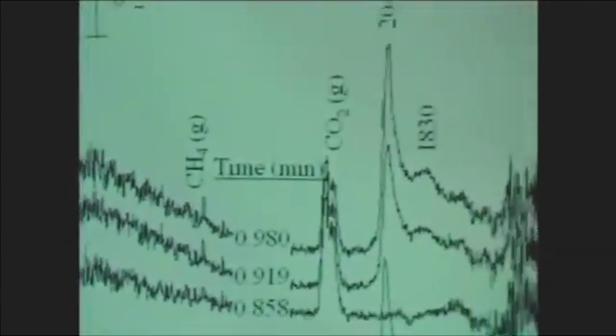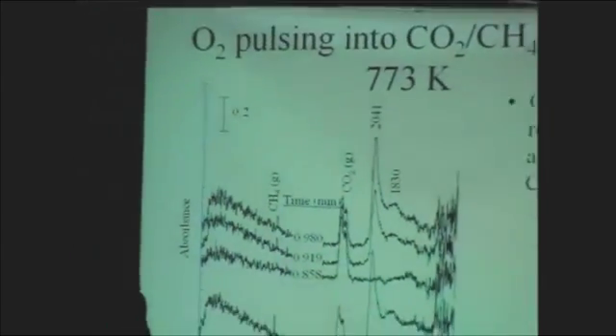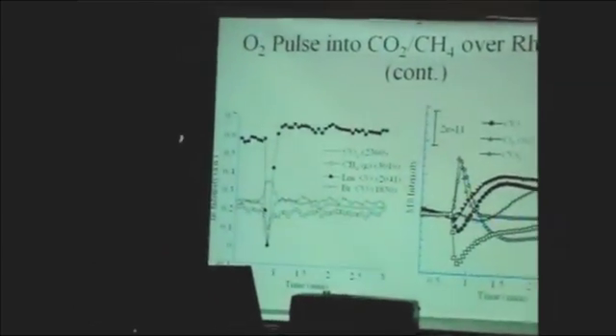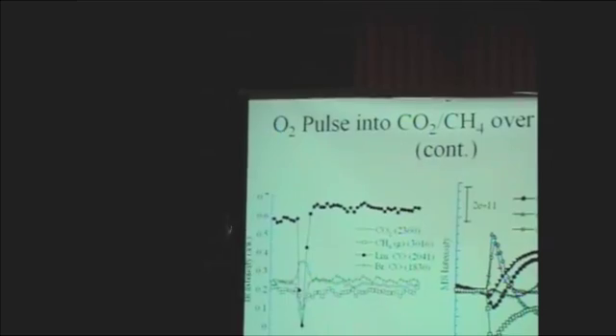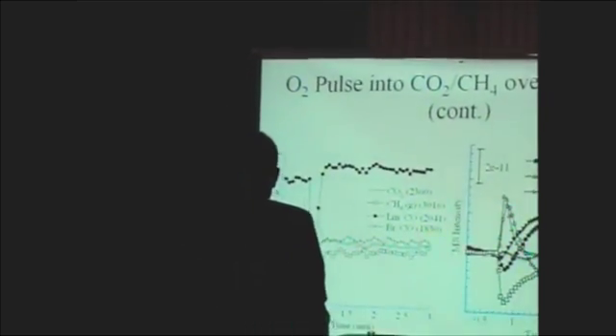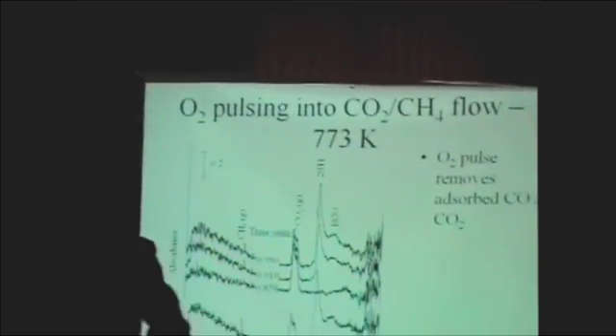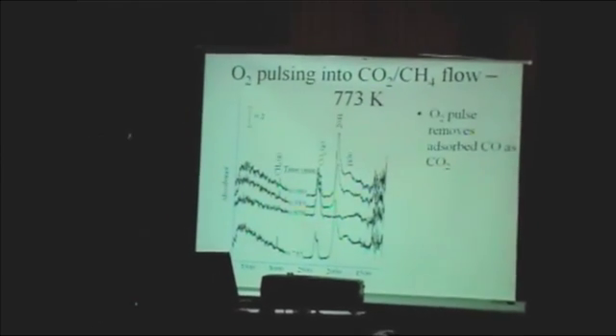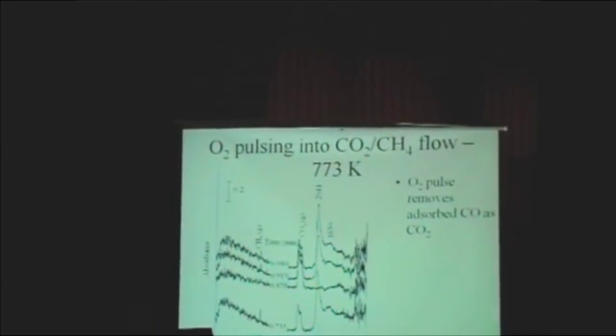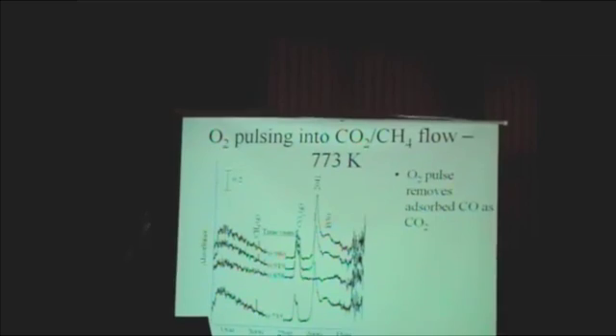So we often like to run any reaction with oxygen in a pulse manner. We control the limited amount of oxygen into the reactor. So in this case, we pulse the oxygen in, and let's see what happens if we pulse the oxygen into the reactor here. The first one is, when we have 15 cc per minute of CO2 and 15 cc per minute of methane flowing through the reactor, and we pulse 1 cc of oxygen in.